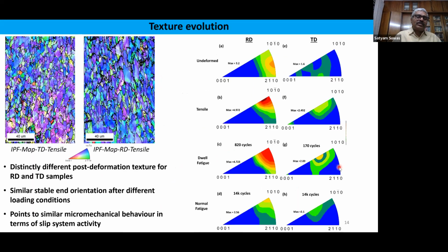And then we examined the formation of texture in this material. The way these grains hardened, or the way the texture evolution took place after deformation along the rolling and transverse directions, made a contrast here. For example, the sample extracted along the transverse direction and subjected to tensile test has undergone stronger changes in texture, or has textures which are slightly different from the one along the rolling direction tested sample.